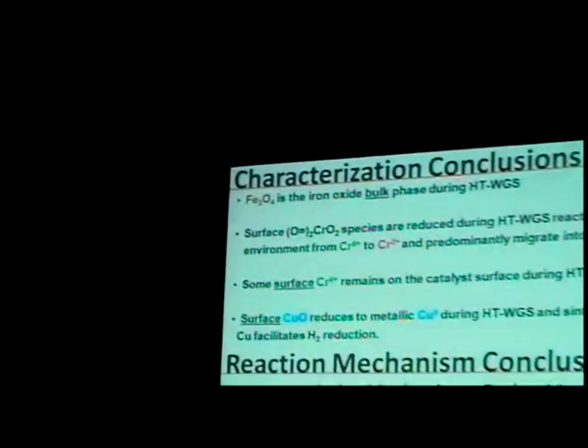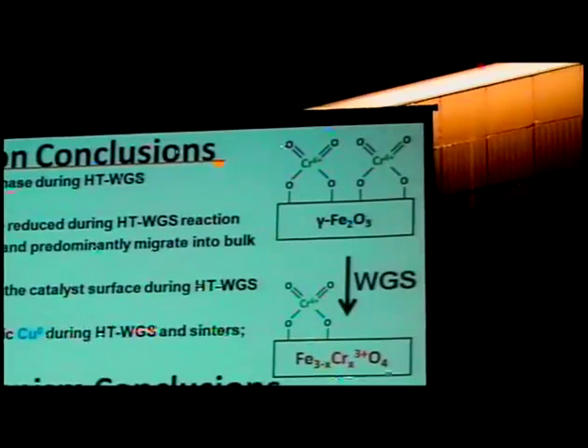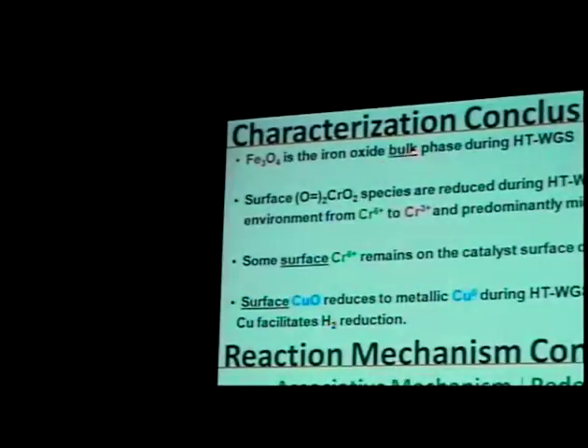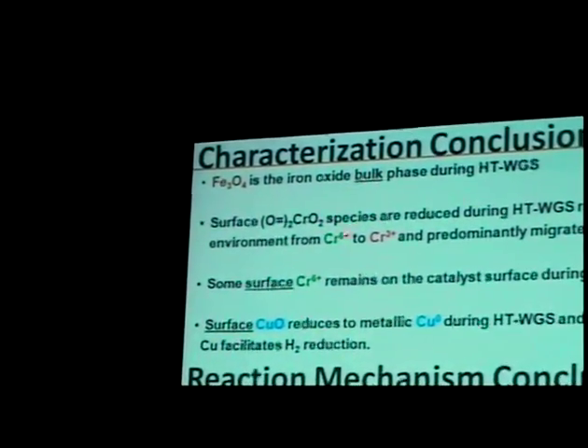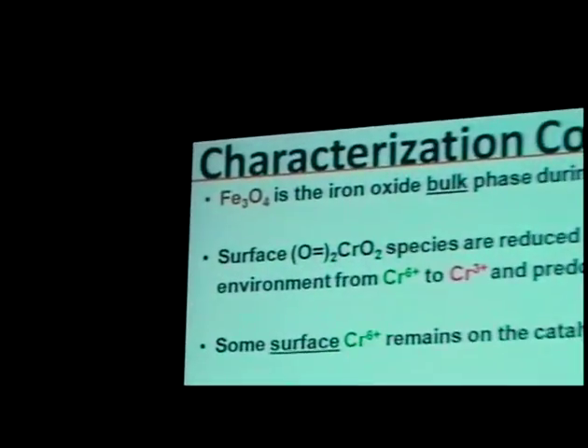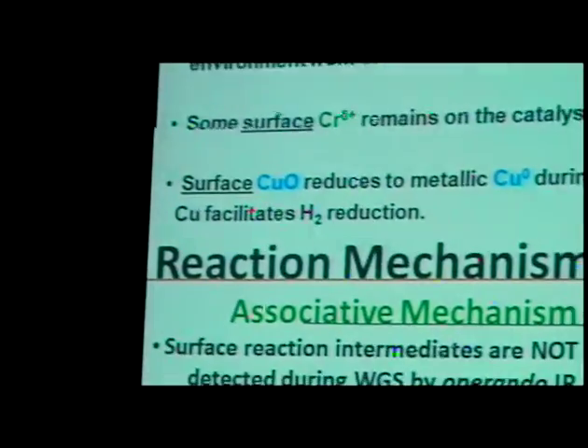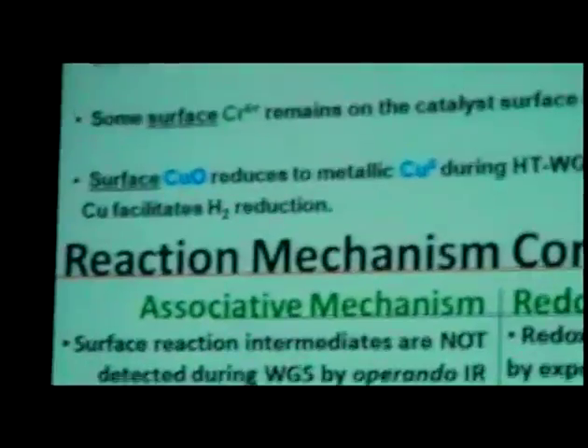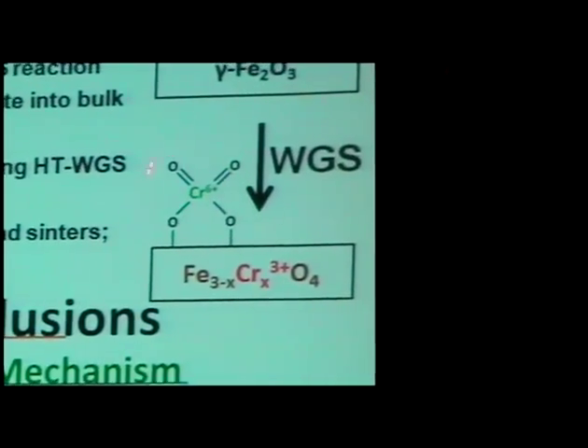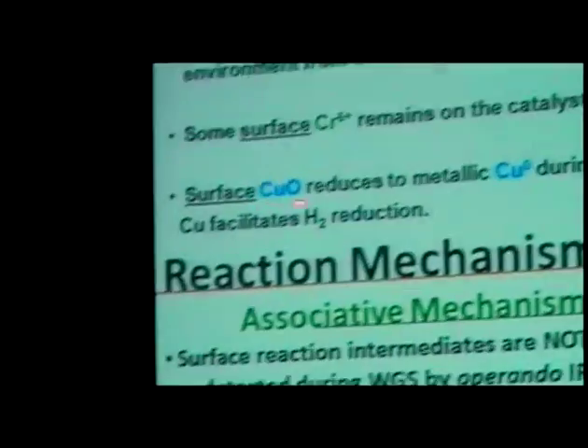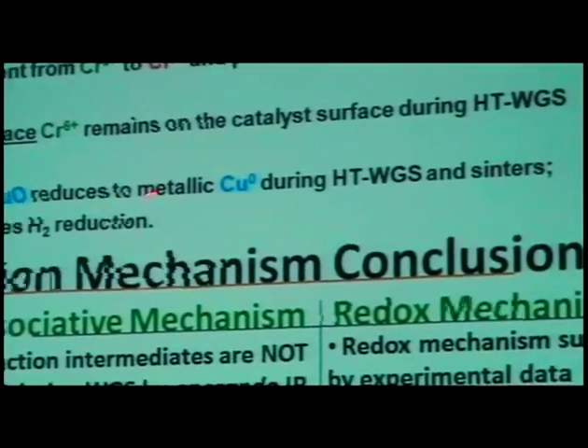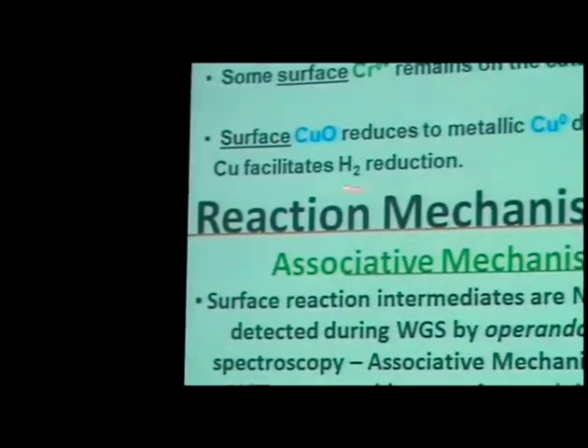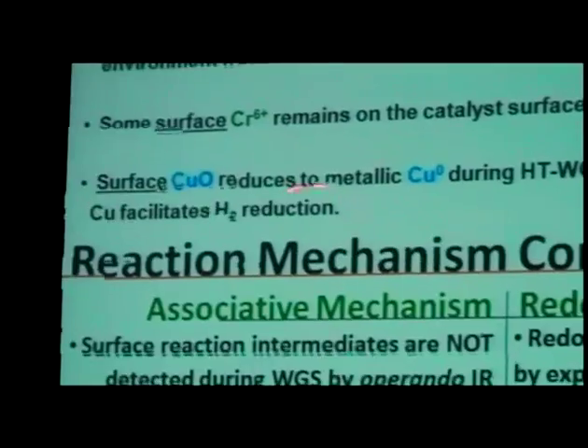So to conclude, the characterization shows that Fe3O4 magnetite is indeed, as claimed in the literature, the bulk iron oxide phase. But again, most of this has been after the reaction. Literature has totally negated the possibility of chromium-6 being present, and we do find that these species are present, although the majority of them are reduced to chromium-3, where Cr2O3 is isostructural with Fe2O3, and the chromium dissolves, but there's still maybe 15% residual chromium-6 that's redox active, and plays a very important role as a catalytic site for the water gas shift. The copper oxide that's there reduces to metallic copper and sinters. Its role is to facilitate hydrogen reduction of the catalyst.